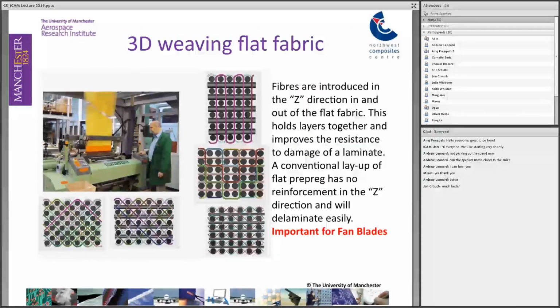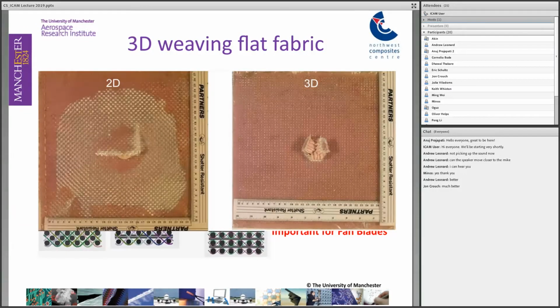The third option that we have with composites in the effort to improve damage resistance and make them more damage tolerant, of course, damage tolerance means that you can still perform your task in the presence of damage, is third dimensional reinforcement. 3D woven fabrics provide us with the ability to delay or prevent those delaminations. Under an impact event, we can compare the two-dimensional fabric under the same impact conditions with a three-dimensional one where all the delaminations have been prevented. Extensive delamination develops in the two-dimensional material, but not in the 3D.